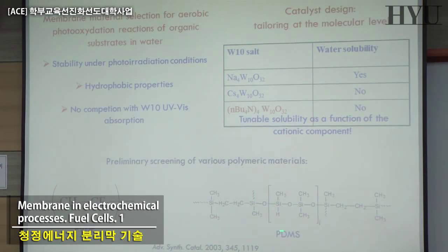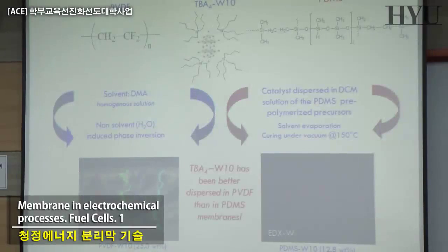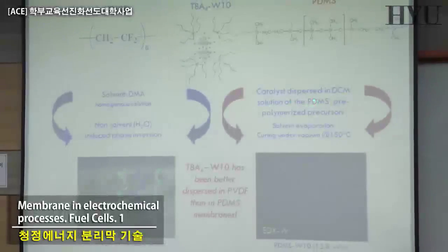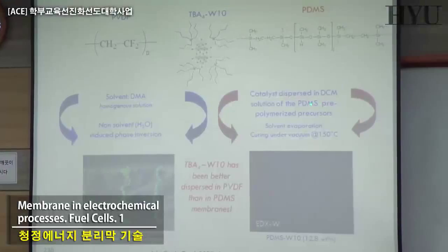And when we made it, for example, we made mistakes. We had no idea, and we have been using PVDF and PDMS, and you will see that not all these polymers are appropriate. At the end, after making this study, you will realize that the system in some situations is working, in some other ones it is not working. And that's what you have to expect. For example, in this case, you have the catalyst dispersed in DCM solution of PDMS for this kind of polymer.